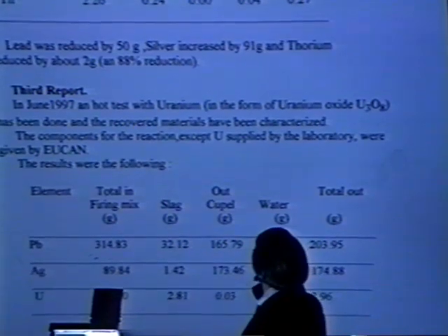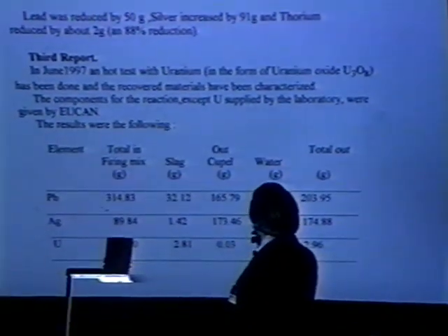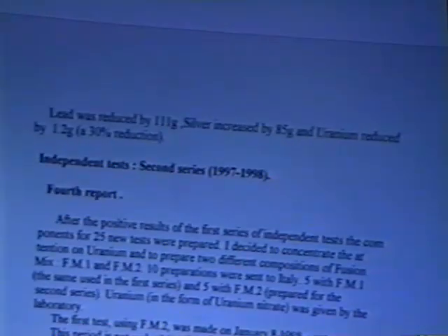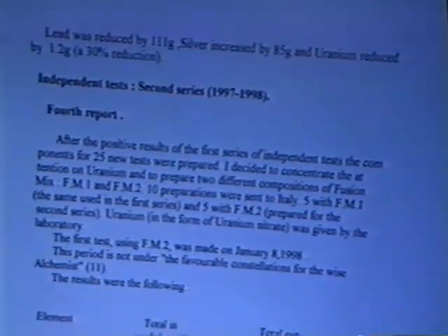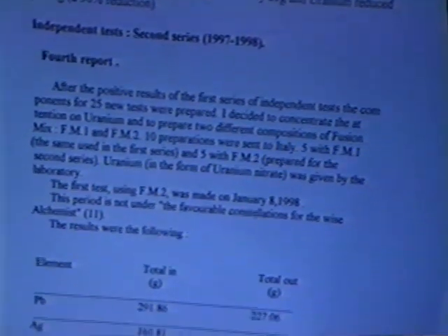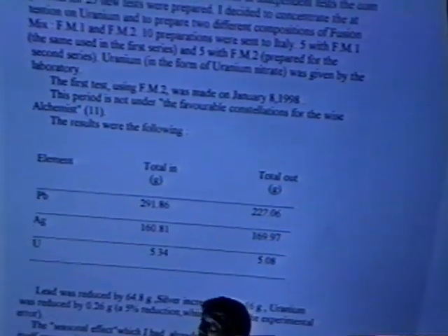So I made the second test with uranium. Note the date: this test was made in June 1997. The result was that lead was reduced by 111 grams, silver increased by 85 grams, and uranium reduced by 1.2 grams, a 30% reduction. In this previous test the seasonal effect is already present, because the test made in May with thorium was 88%, and the test made in June was already going down to 30%.